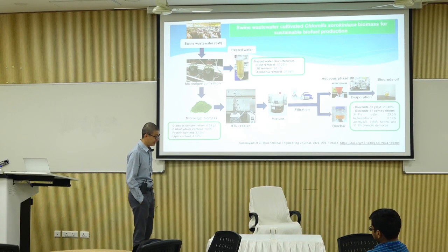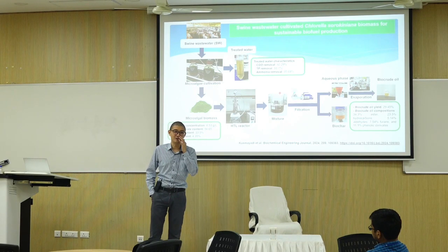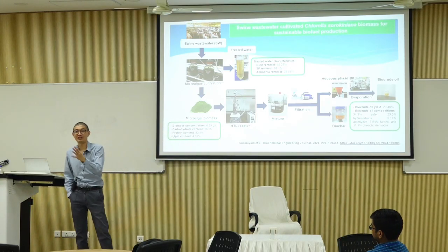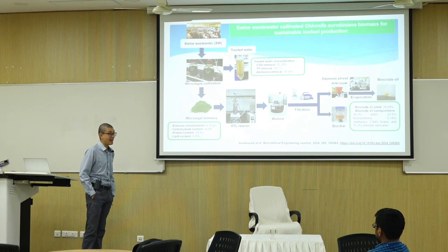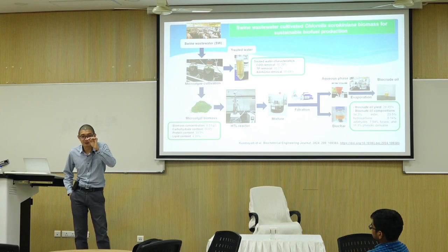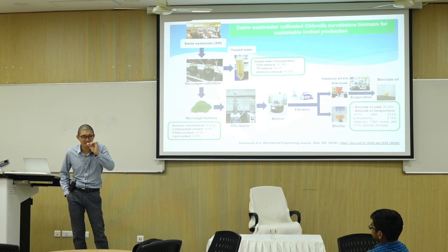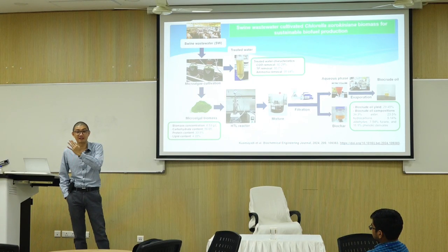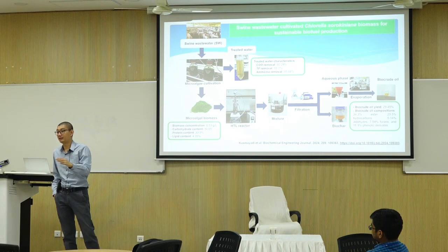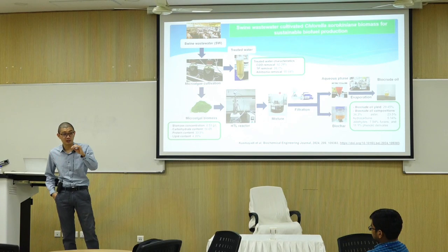Most of the industry is still using the open dry process for mass production of biomass. Unless the product has to be controlled to a very precise percentage of moisture content, then you have to go through the industrial process. After the open dry process, you go through maybe the oven dry or another process to make sure the moisture content is lower than a certain limit.